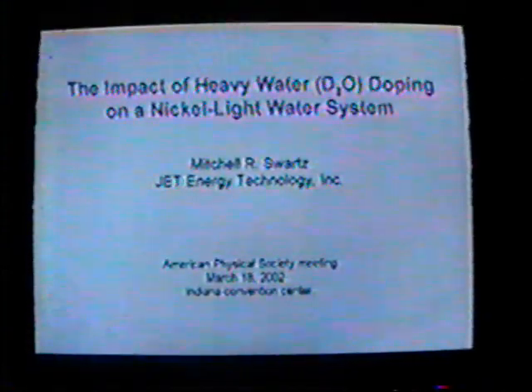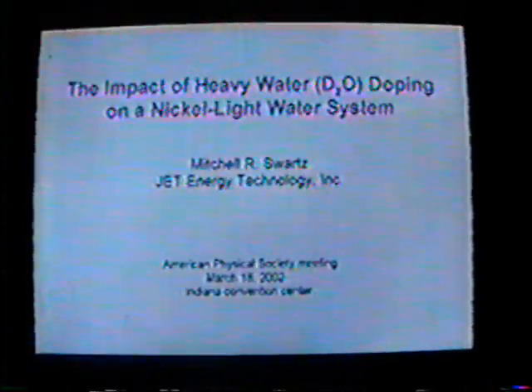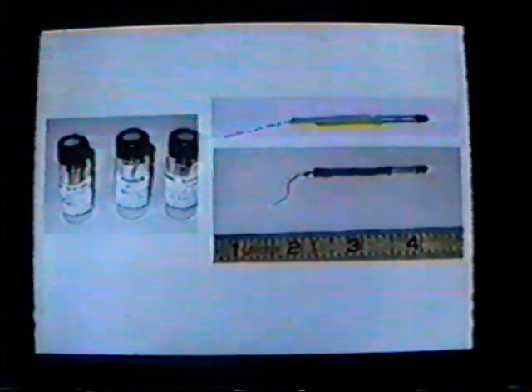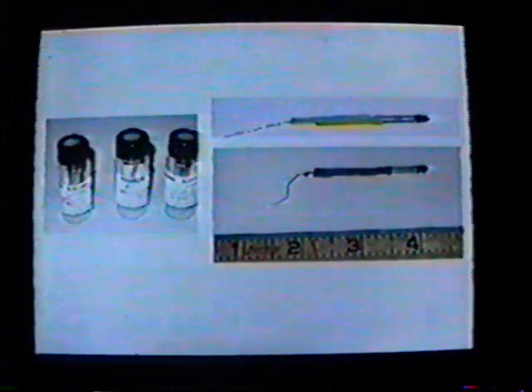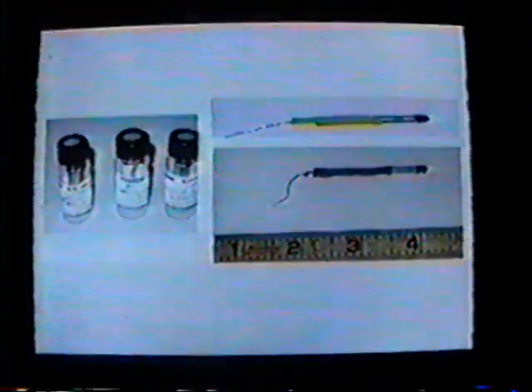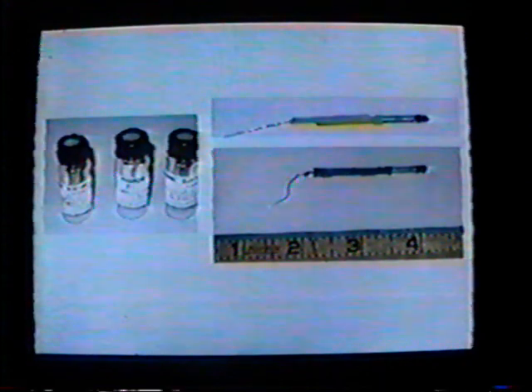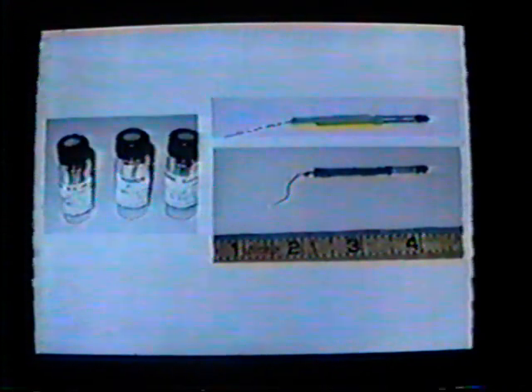In these experiments, the cathodes used were spiral, gas-free nickel, cold worked, which were set up against a platinum plate. Electrical resistivity of the electrodes was determined by 4-terminal conductivity measurement using an electric current source and a high input impedance electrometer. Geometric factors were determined by caliper.